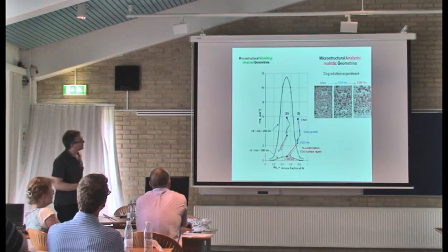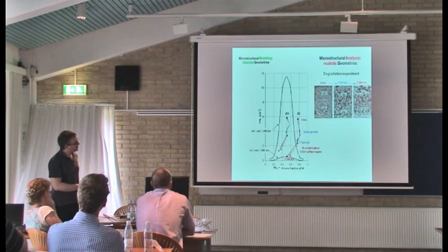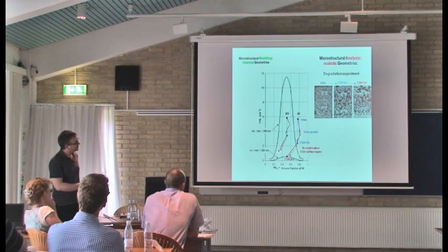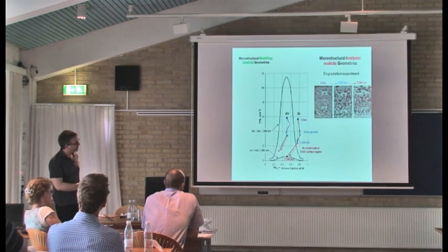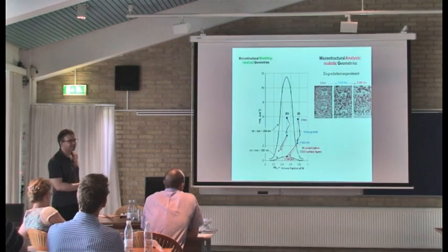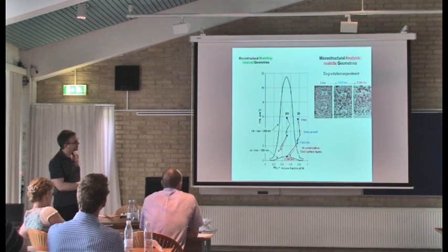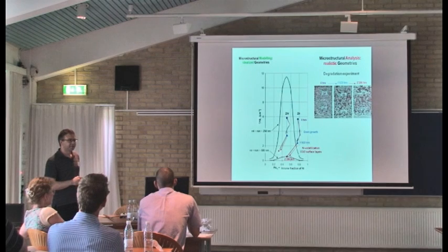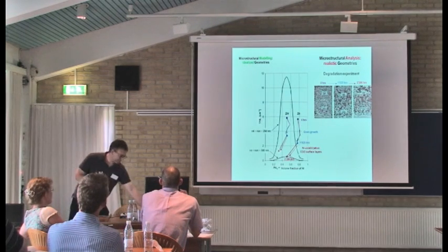I go directly to this: in the first phase we have this grain growth, and in the second phase we have a reorganization where nickel becomes volatile, and where we have the formation of these surface layers, which also leads to a reduction of TPB.